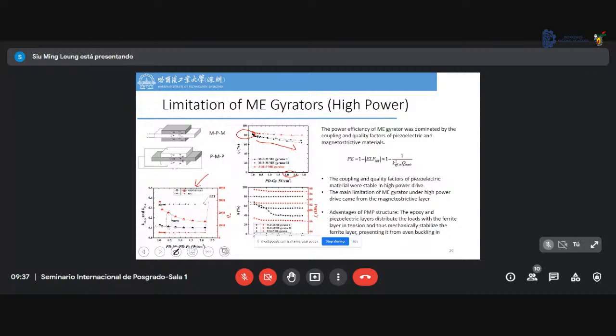So the first step I tried to solve this problem is to choose another kind of configuration. For the original one, we use two magnetostrictive materials, and then we sandwich them with one piezoelectric material. But we find that the problem usually comes from the magnetostrictive material, so we try to use only one magnetostrictive material and sandwich it with two piezoelectric materials, and we watch the mechanical damping on the magnetostrictive material and make it have a higher power.